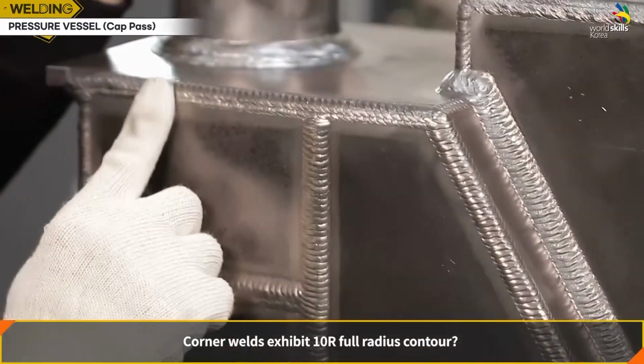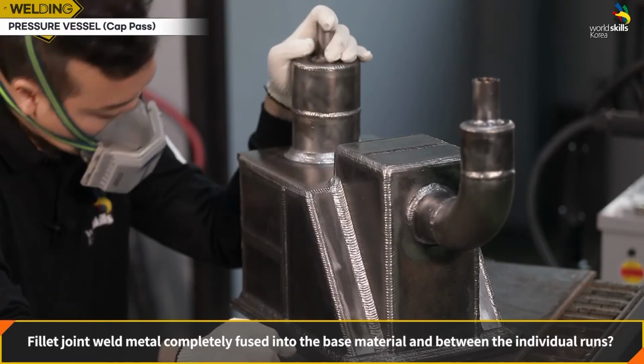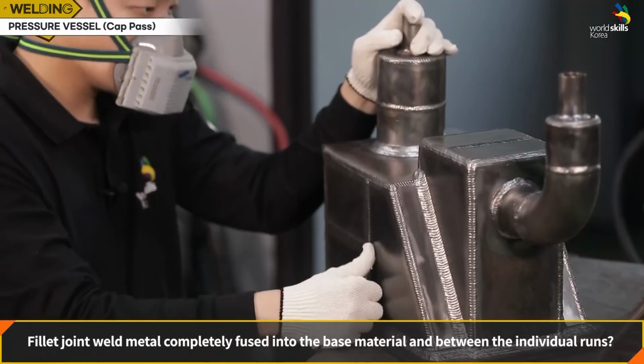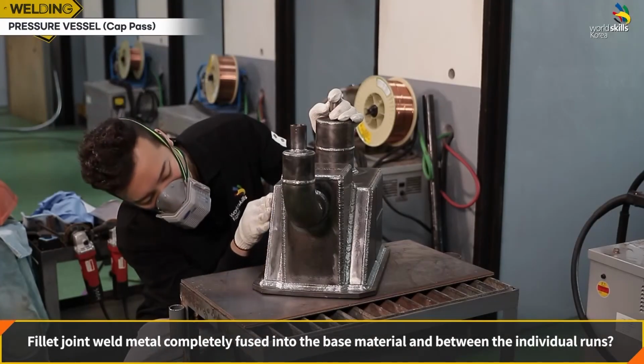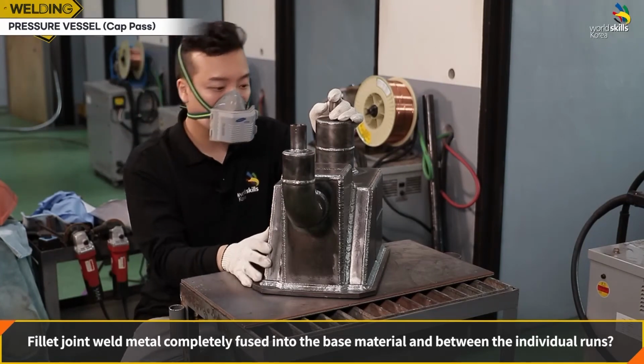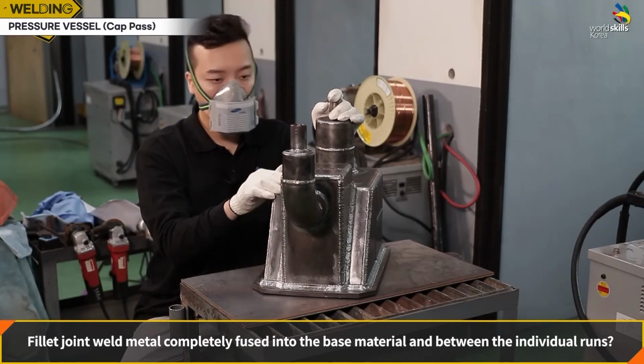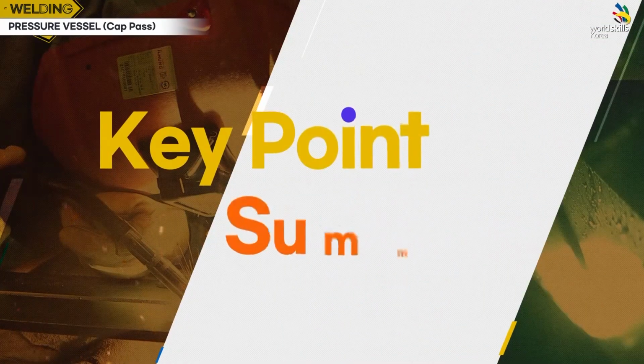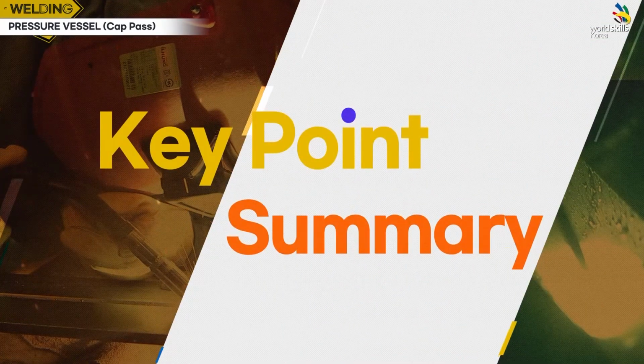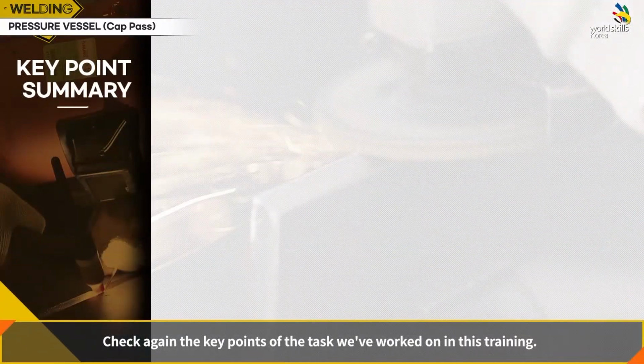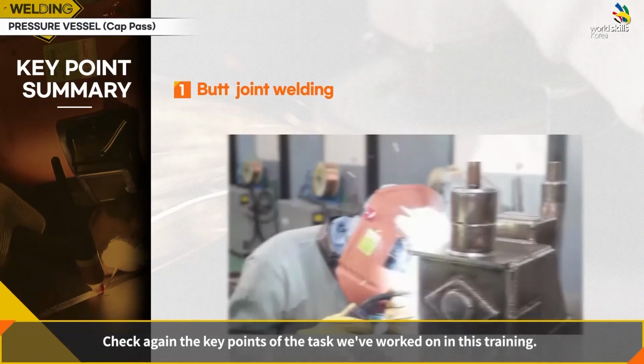The R value of the corner should be 10R. Also, check whether the R value came out correctly. Check if the fillet joint weld metal is completely fused into the base material and between the individual runs. Please check the key points of the tasks you have done this time.